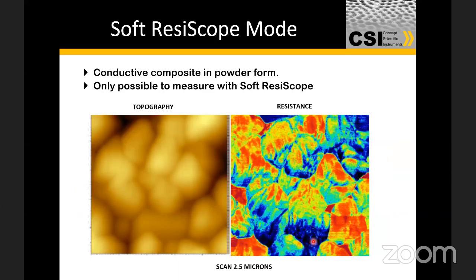And again, this is another polymer surface. The image on the left is classical of some sort of a polymer blend. What we're trying to highlight here is that because we have this soft technique of the resiscope, we are able to bring out the resistance of this surface with a resolution that you would struggle to get with an ordinary conductive AFM technique, because of the nature of the surface, how soft it is, how sticky it is, and its underlying topography as well. And this represents a scan size of about 2.5 microns.